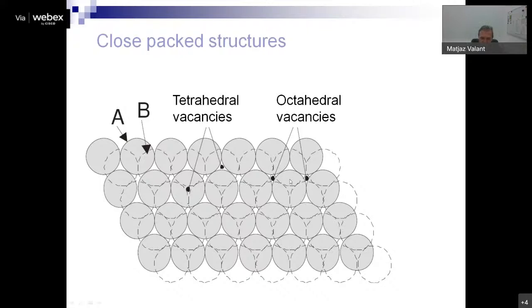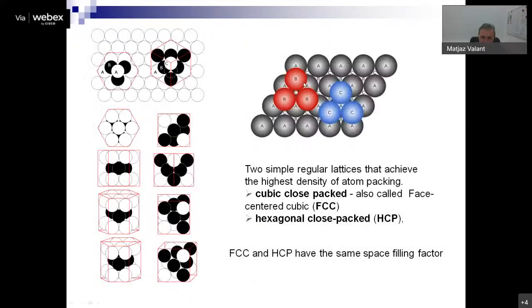Why is this important? It's important because when we put the 3rd layer on the top of these 2, we have 2 different possibilities. We can put it like it's shown here, where we cover the tetrahedral vacancies, or we can put it like it's shown here, where we cover octahedral vacancies. So we would have 2 different close packed structures. One close packed structure would be called cubic close packed structure, because the unit cell that we define out of these stacks is a cubic one, and it's represented here.